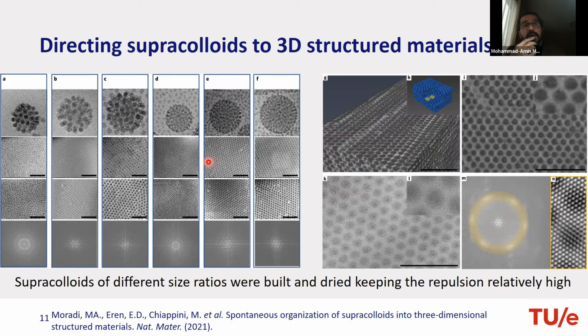So, and then we analyzed them via STEM tomography in some cases, and we could see the order inside the material. So you can see several layers of the material, nicely compact, and then having the silica particles in between. And these silica particles are so stable that even after calcination and removal of the polymer, you can still see the structured materials in some cases.